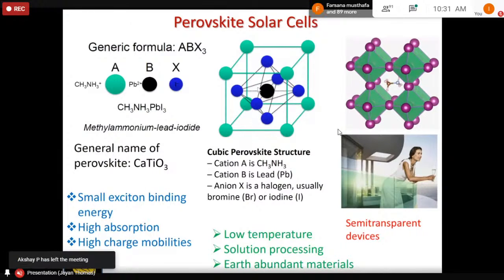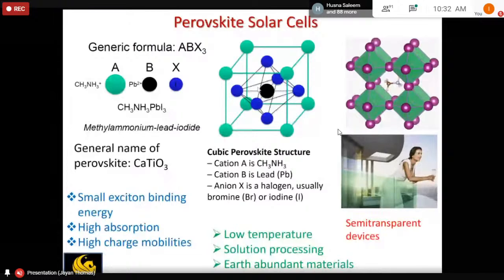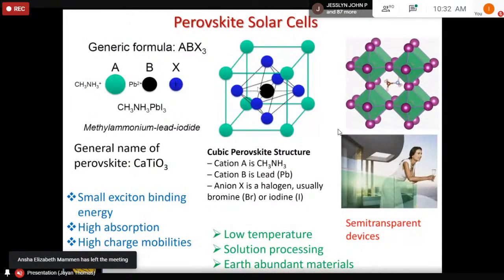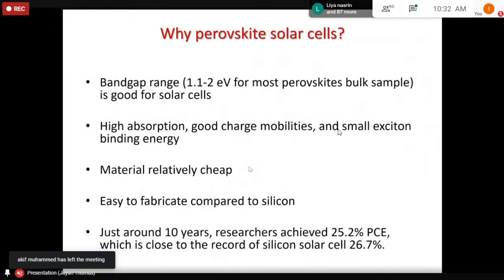And when you consider the thickness of these solar cells, the silicon solar cell you buy from the market is about 300 microns thick. That is the thickness of a silicon solar cell. Whereas the perovskite solar cell requires only 300 to 350 nanometers to convert the same amount of input sunlight, compared to 300 microns in the case of silicon. So you need a much smaller quantity, and this perovskite can be made by just solution processing, whereas in the case of silicon, high temperature processing is required, which takes a lot of energy too.